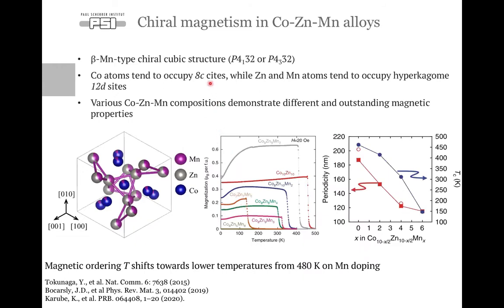Let me introduce you to chiral magnetism in exotic cobalt zinc manganese alloys that crystallize in the chiral cubic structure of a beta-manganese type, which belongs to the space group P4132 or P4332, depending on chirality, where cobalt ions, shown here as blue spheres, tend to occupy 8c sites, while zinc and manganese ions, shown here as gray or pink spheres, respectively, tend to occupy 12d sites, forming a hyperkagome, frustrated three-dimensional triangular lattice.